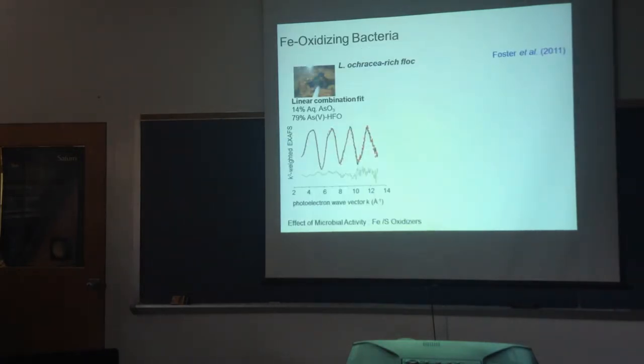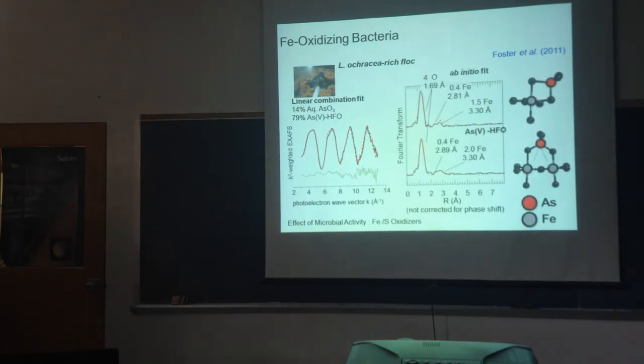So when Andrea Foster analyzed this material, she saw, using the XAS technique, which again is the synchrotron radiation, that there was arsenic associated with the most oxidized form in all these cases, and that she uses various techniques such as linear combination, ab initio. These are basically different ways of trying to fit the curves you get from the synchrotron and try to understand the speciation. But basically, it's the